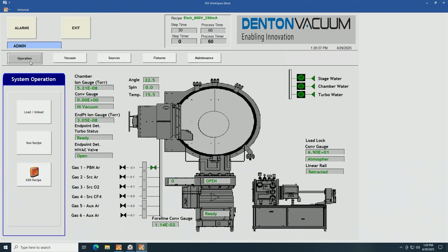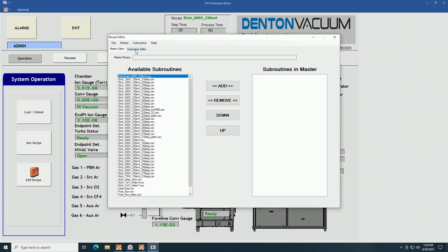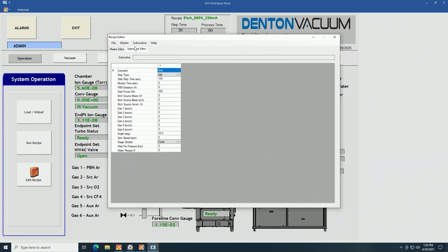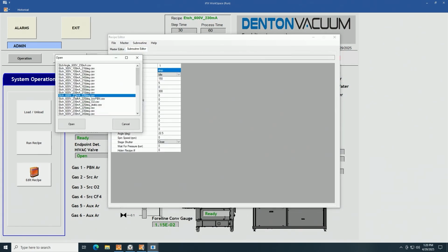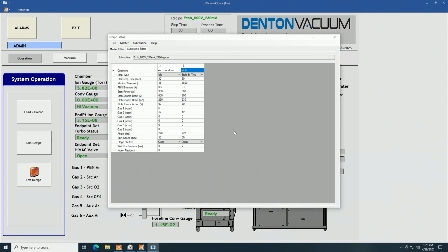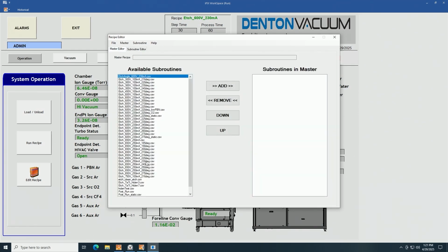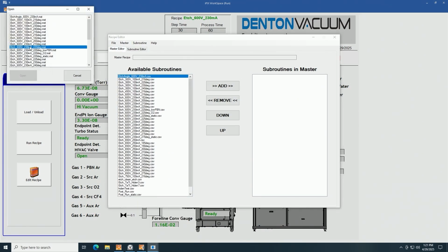Starting here, the operations screen, this is where you would run a recipe. Here's what the recipe editor looks like. It's built around sub-recipes. I'll open one as an example. Here's one for etching at 220 degrees. First it goes to the etch condition and waits for 30 seconds, and then it actually does the etch with the shutter open. The usefulness of the subroutine design is that you can chain together recipes. So my actual recipe for that 220 degrees is going to look like this.